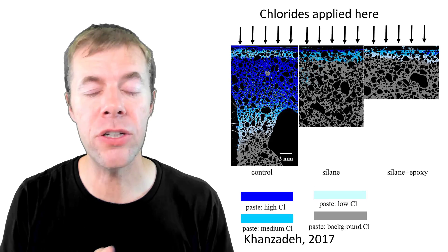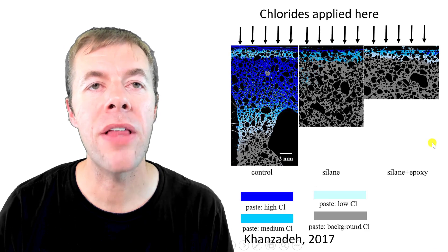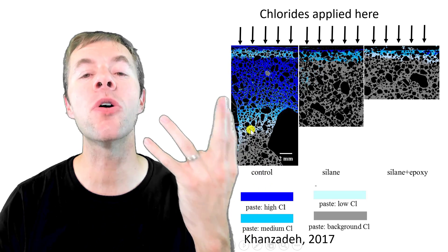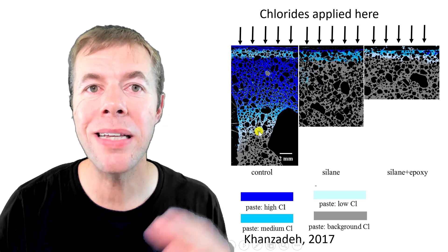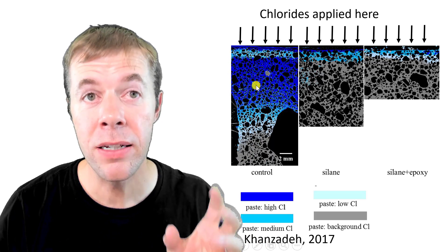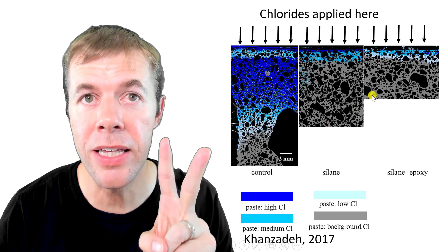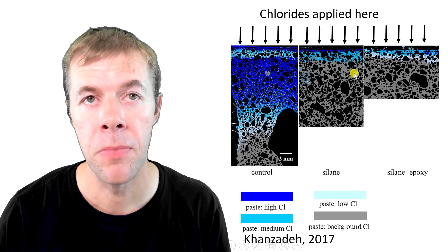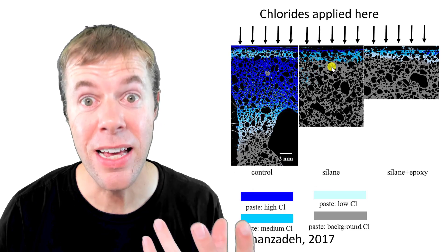If you try to put chlorides into these structures, this layer is going to help hold those chlorides out. On the left, this is concrete that was not coated with anything, and we can see the chlorides have penetrated. This is a chemical image — the gray value is the background meaning no chlorides, light blue means low chlorides, and brighter colors mean a higher concentration. This is after 180 days — look how deep it's penetrated. Now this is the exact same concrete but treated with this silane material at the surface — look how it's holding the chlorides back, look how it's not getting in very deep. This is the type of performance you want from a membrane on your concrete.